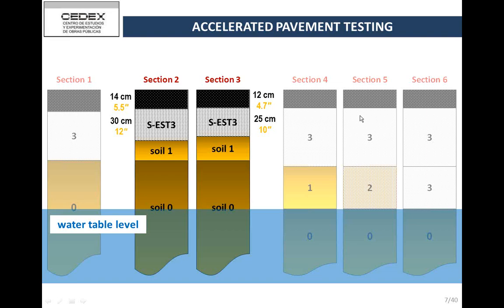Australia has delivered a nice report on the performance of lightly cementing layers. I didn't have the time to read it, but it seems to be a very interesting one. In the US, we typically don't go with such a low cement percent. We typically go somewhere around 8 to 10% cement. But we still have the same problem because of the drying at the very surface of the soil cement. What is critical is after you place the soil cement, how do you seal the surface and how fast do you come with the asphalt on top?